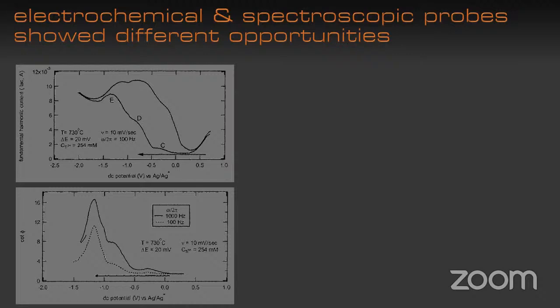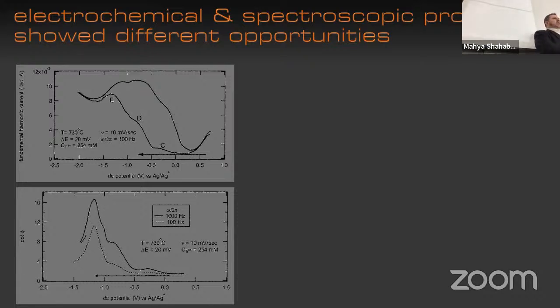But as soon as you start to get into the AC space, you have other measurables that start to become electrochemically important. So, for instance, if you look at the bottom one, if you look at phase angle, you start to have a much more peaked response, as opposed to looking at too many shoulders. If phase angle turns out to be the strongest, easiest response in your voltammetry, then now you have something that not only is a nice peak, but is also changing with concentration. And those are the two pieces that you're seeing in this rudimentary approach here. So electrochemically, we have an approach that could give us something that varies with concentration,